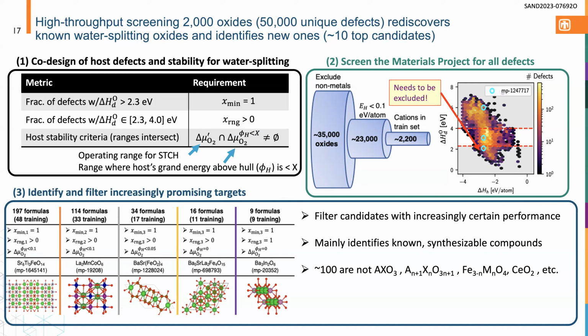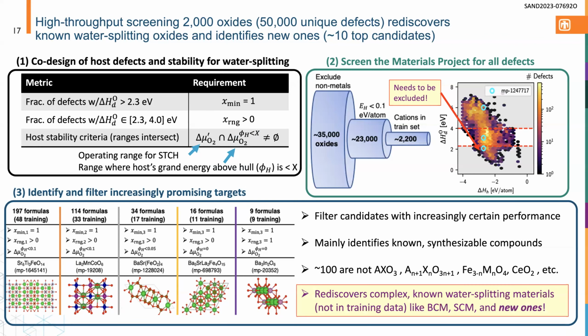It mainly identifies known synthesizable host structures because we're, again, dealing with Materials Project, which is based on the ICSD. And some materials popped up that weren't the typical suspects of ABO3 perovskites, Ruddlesden-Popper phases, mixed metal ferrites, etc. And so this screening process rediscovered known materials. So BCM was a crystal structure in Materials Project. It rediscovers it as being a potential water splitter. And we've now identified new ones that the experimental team is working on. And they do have a manuscript in preparation on some of the materials that they've looked at based on this study.